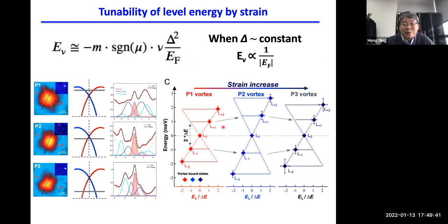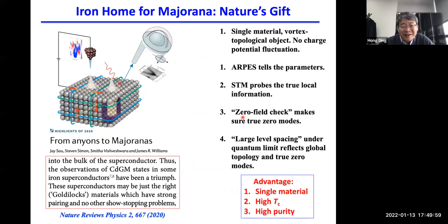And we wanted to do this QPI to see how this separation changes in situ and to demonstrate all of this. According to simple quantum mechanics, we will see this is indeed the Majorana zero, one. So we actually find that the iron-based superconductor is a Majorana home, which is actually nature's gift. It provides us a single material with the vortex, which is a topological object.